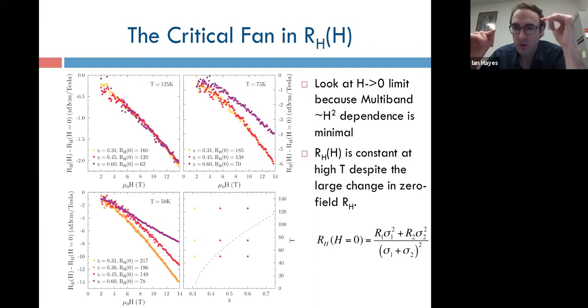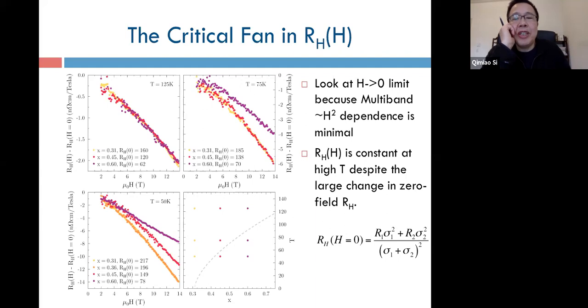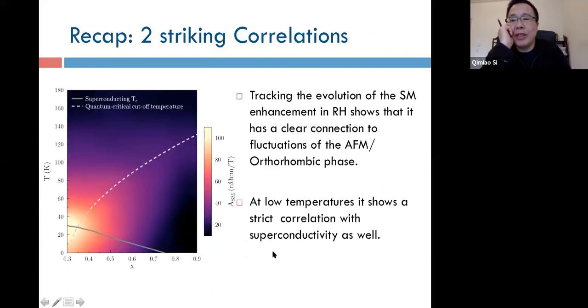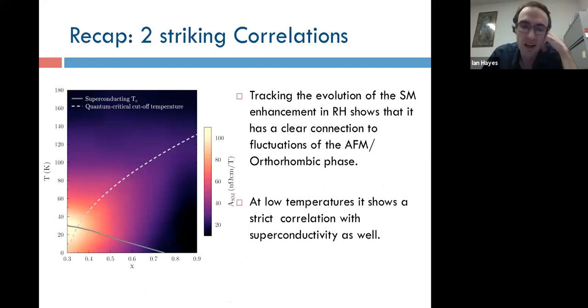Yeah, so a question of how quick the transition is between, say, the totally normal Hall coefficient on the overdoped side and the optimally doped or underdoped behavior? Yeah, because you refer to the strange metal component of the Hall, and one could perhaps look at that. Yeah, it's a good question. Looking at it in detail will be a little tricky because of the limits of high field measurement. Broadly, as a function of temperature, it sharpens a bit. So just looking at the color plot here, you can tell that there's a broader region of enhancement at intermediate temperatures, and it kind of sharpens up as you go towards lower temperatures.